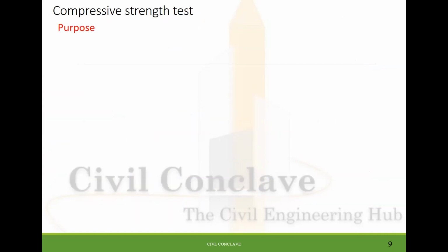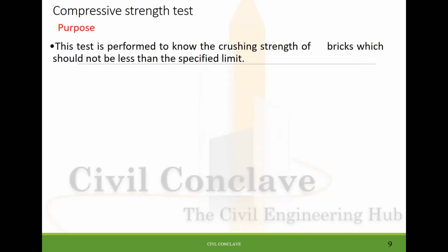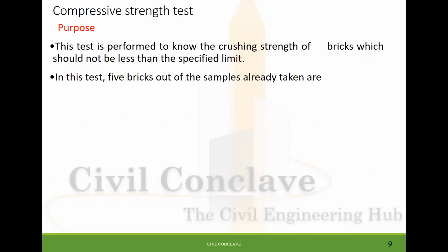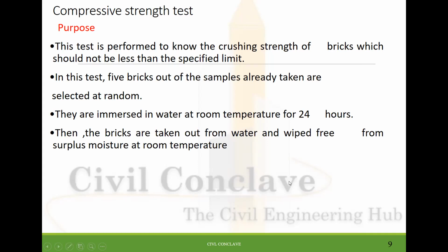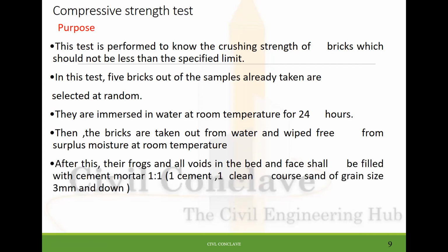Compressive strength of the brick test. The purpose of this test is to find out whether the brick has the desired compressive strength as stipulated in the codes. In this test, we take 5 samples, which have been already selected randomly. They are immersed in water for a minimum period of 24 hours. Then the bricks have to be taken out of the water, the surplus water wiped off, and kept for a certain time at room temperature.